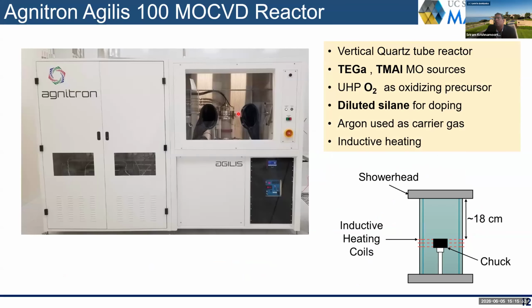In my group, we do both growth and devices. In terms of growth, we use an Agnitron Agilis research reactor with 2-inch capability. We use the standard precursors that are used in other compound semiconductors, like triethyl gallium and trimethyl aluminum, and we use ultra high purity oxygen as the oxidizing precursor. Silicon is a dopant for gallium oxide, silicon substituting on the gallium site as a shallow dopant. We use dilute silane for doping and argon as a carrier gas. Right now the reactor is configured with about 18 centimeters distance between the shower head and the chuck, but we have the capability of bringing this closer, what is referred to as the close injection shower head geometry. That's part of our future plans as well.